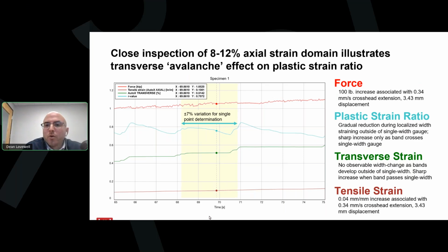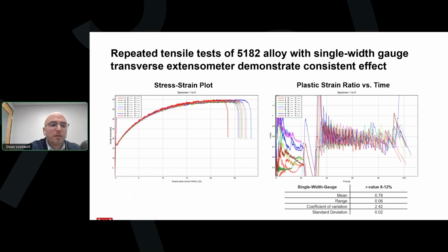But then as the localized width strain occurs elsewhere, and we have the plateau in the transverse strain curve, R value is perceived to decrease until a band crosses this width again. And this behavior is consistent across the 5182 alloy specimens we tested.